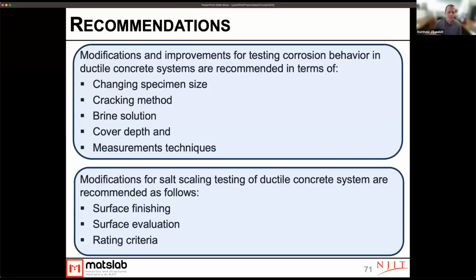In terms of testing corrosion behavior in these ductile concrete systems, looking at specimen size, changing the cracking method, brine solution, cover depth, different ways to measure, et cetera, these are all things that we think should be considered when evaluating these systems. With the salt scaling tests, when using these ductile fiber reinforced concretes, thinking about surface finishing and surface evaluation and what rating criteria should be used is definitely something to consider as well.